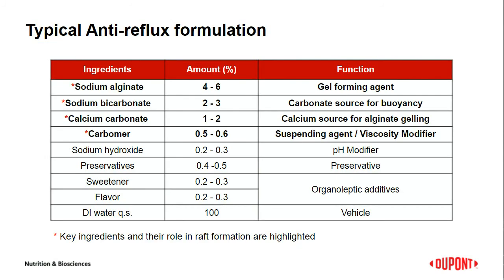For the preparation of anti-reflux suspension formulations, the ingredients used are tabulated with their concentration and functions. The key ingredients used in the raft-formation suspensions are sodium alginate, which acts as a gel-forming agent, sodium bicarbonate, which acts as a carbonate source for buoyancy, calcium carbonate, which acts as a calcium source for alginate gelling, and carbomer, which acts as a suspending or viscosity modifier. Apart from these key ingredients, there are other ingredients which are used as preservatives, pH modifiers, and vehicle.